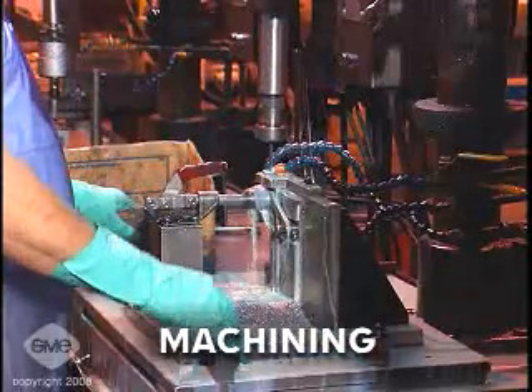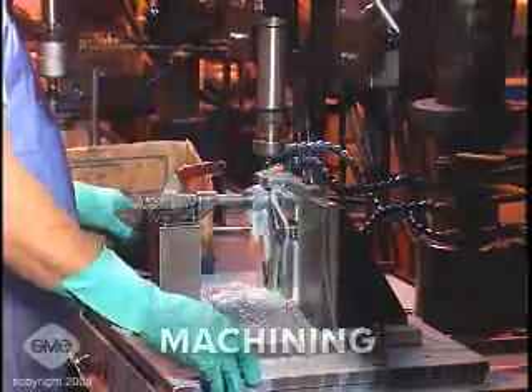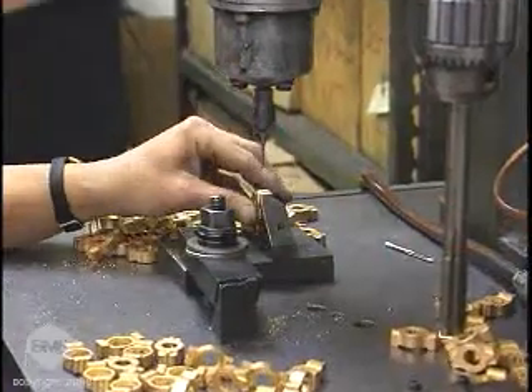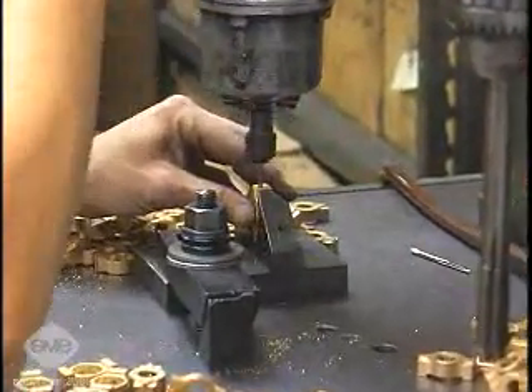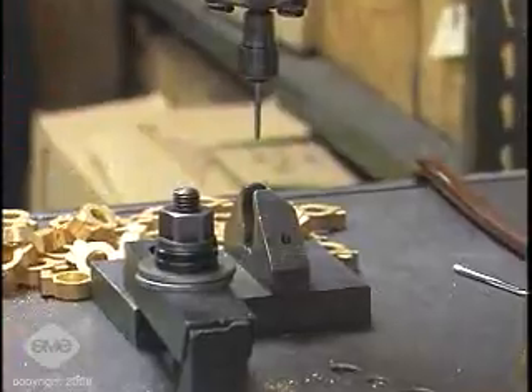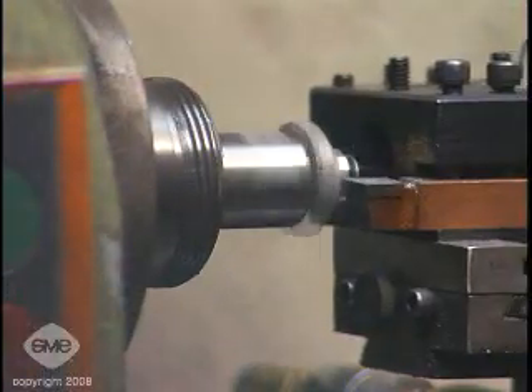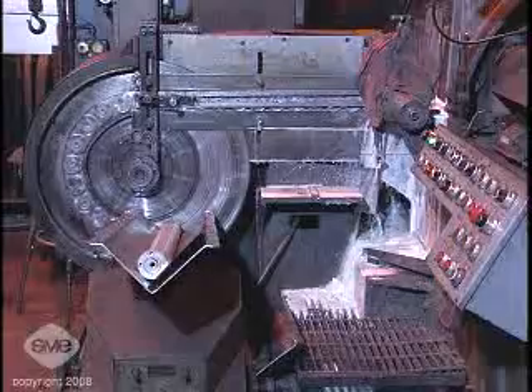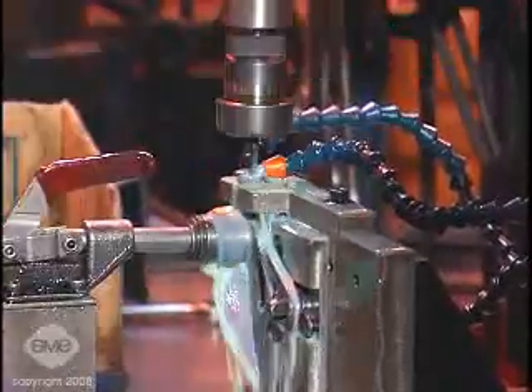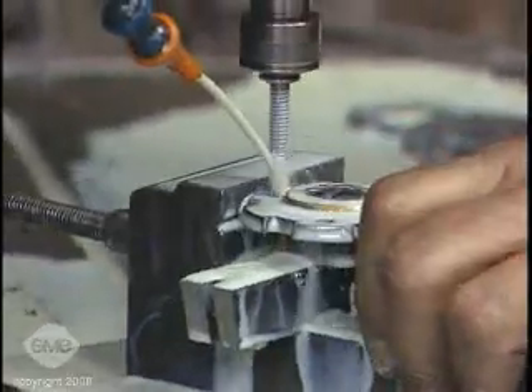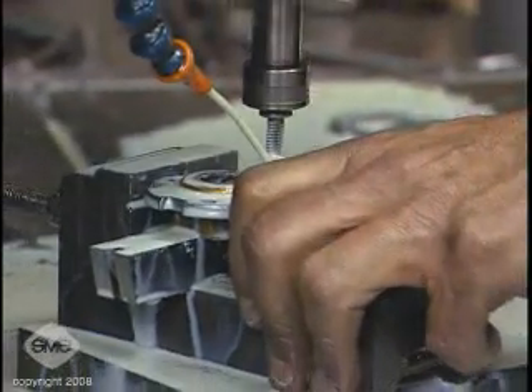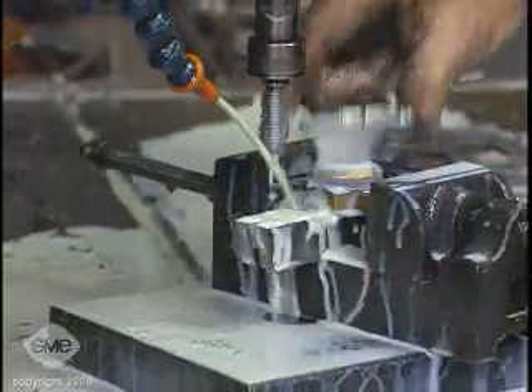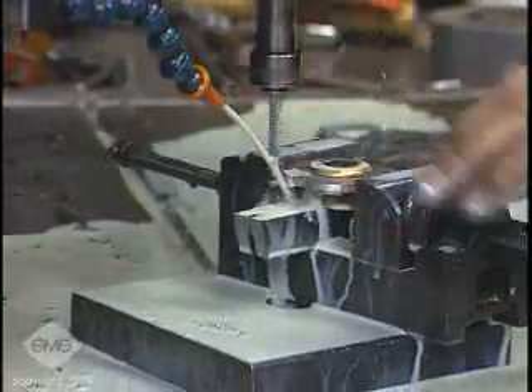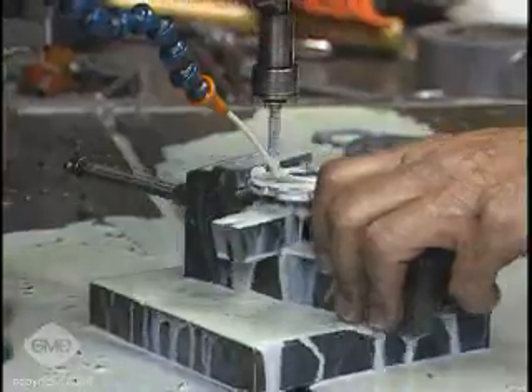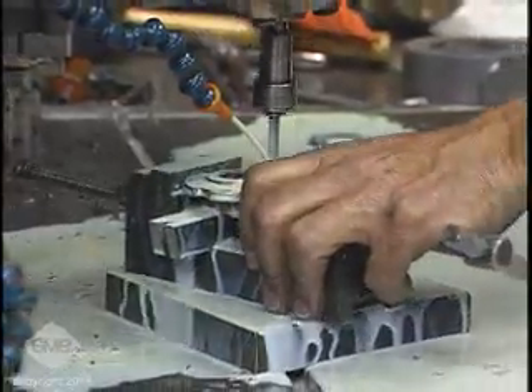Secondary machining operations are needed because side details, such as grooves and holes that are transverse to the pressing direction, are impossible to produce by the vertical action of mechanical pressing. These machining operations include turning, milling, grinding, drilling, and tapping. Choosing the proper coolant is extremely important when machining powder metal parts, especially for porous parts because the coolant may be absorbed and react with the base metal.